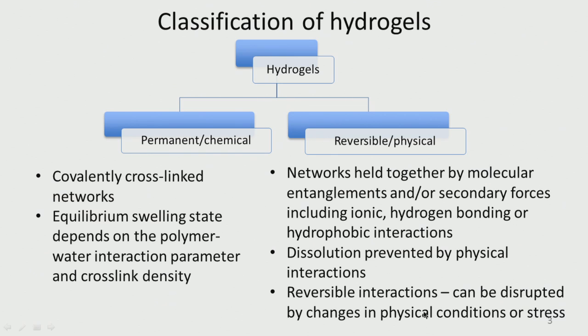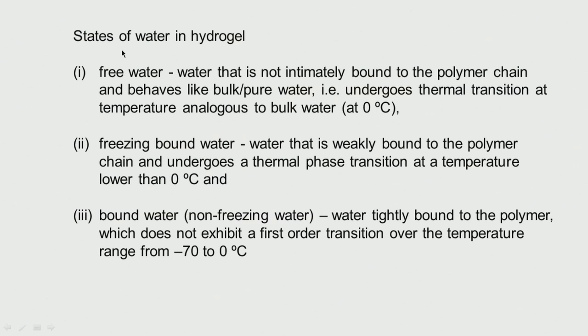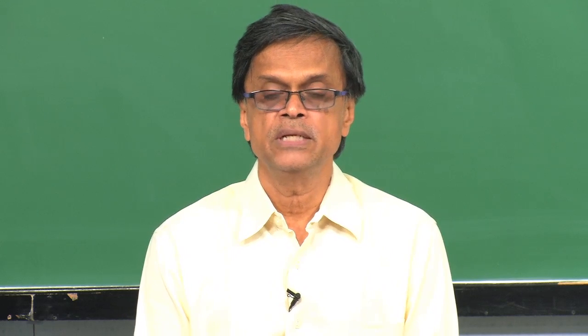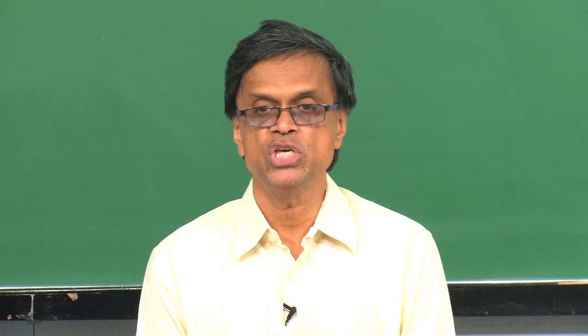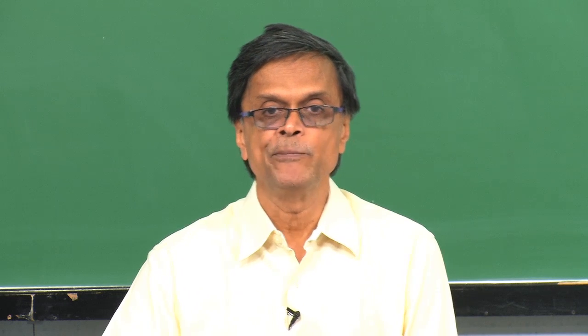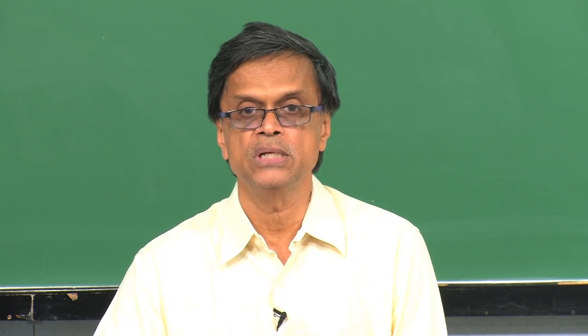There are three types of water in hydrogel. One is called free water — that is the water which behaves exactly like water present in the bulk, like pure water, and it will freeze at around 0°C. Then we have freezing bound water, which is weakly bound to the polymer chain and also undergoes thermal phase changes, but generally below 0°C. Then we have non-freezing bound water, which is strongly and tightly bound to the polymer, so it will not freeze like the other types, and the phase change may happen much lower or may not be observed at all.